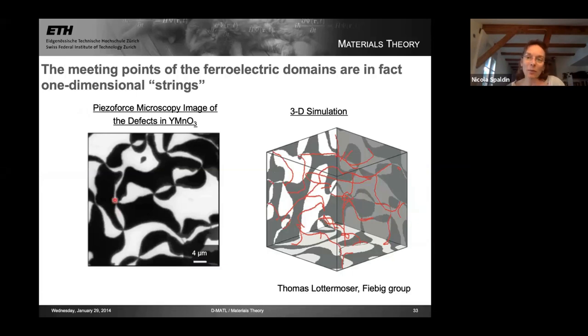Oh, yes, and one more point. The piezo force microscopy image is a two-dimensional cross-section. In three dimensions, these intersections on the surface are actually lines. And this is a simulation from Thomas Lottermoser, also in Manfred Fiebig's group. This is the other simulation that half of you thought were cosmic strings at the start. We would love to have a measurement of these three-dimensional strings. This would be really wonderful, and I'd be really happy to discuss later if any of you have ideas of how to measure it. At the moment, the only measurement we have is Martin makes the piezo force microscopy image of the surface, then he polishes a little bit away, so he moves down in the material, then makes another image, and then polishes a little bit away, and this is obviously rather laborious and also a bit destructive. But these intersections are really one-dimensional strings.